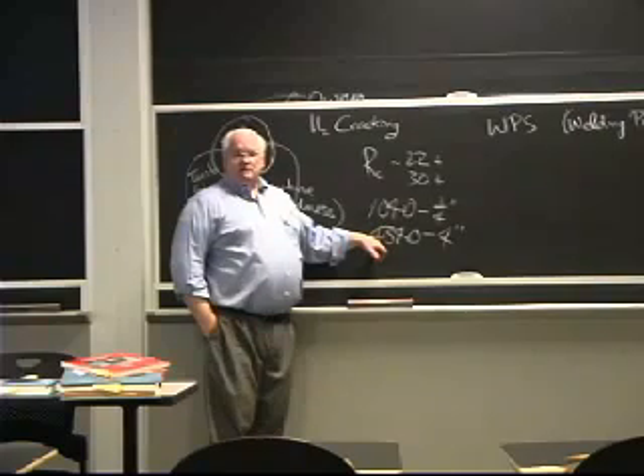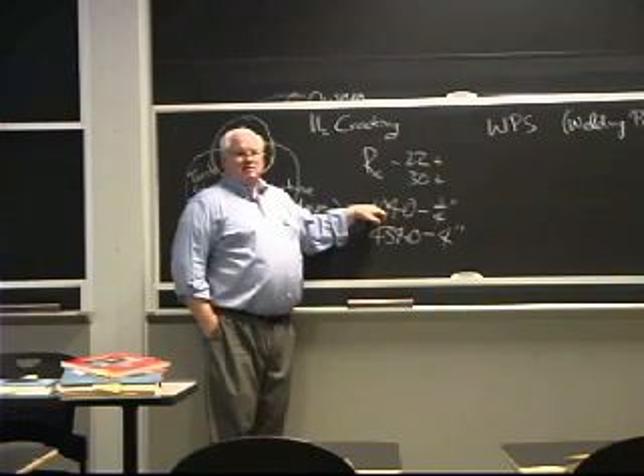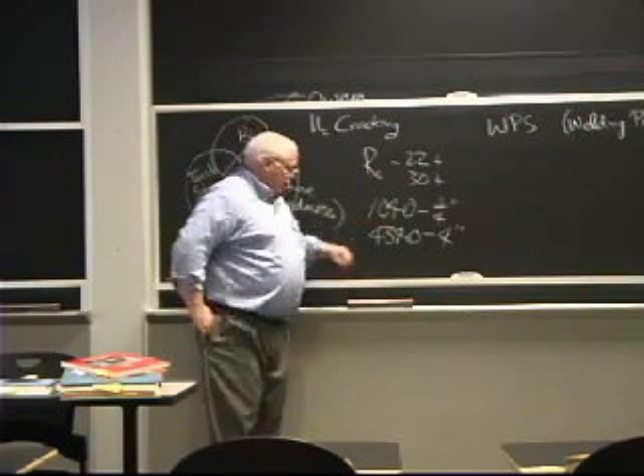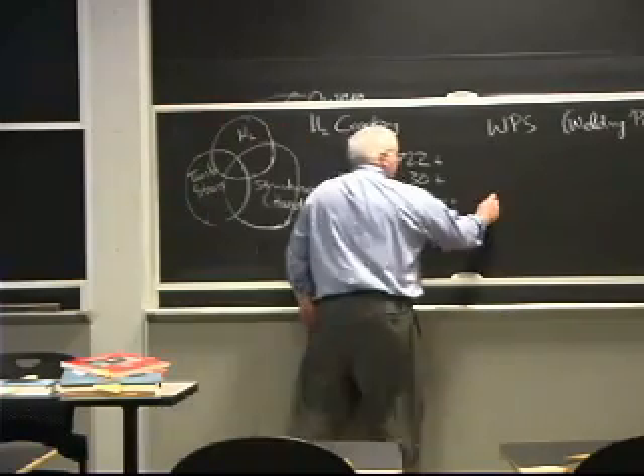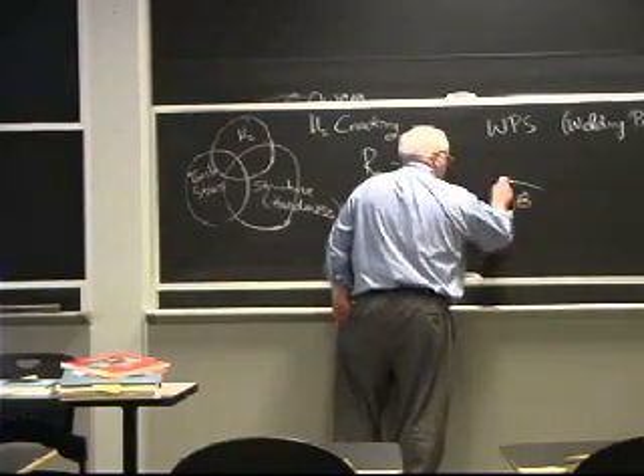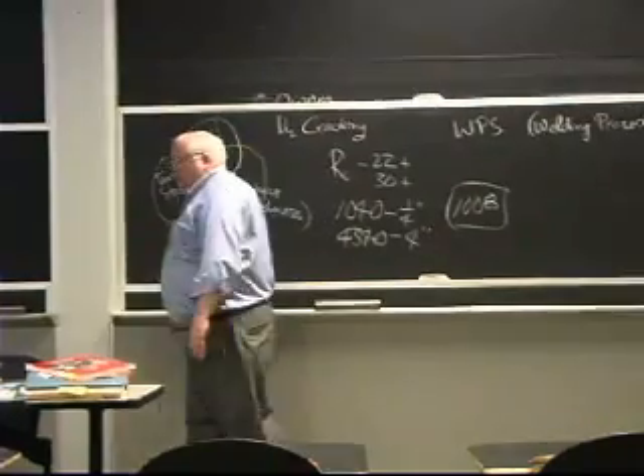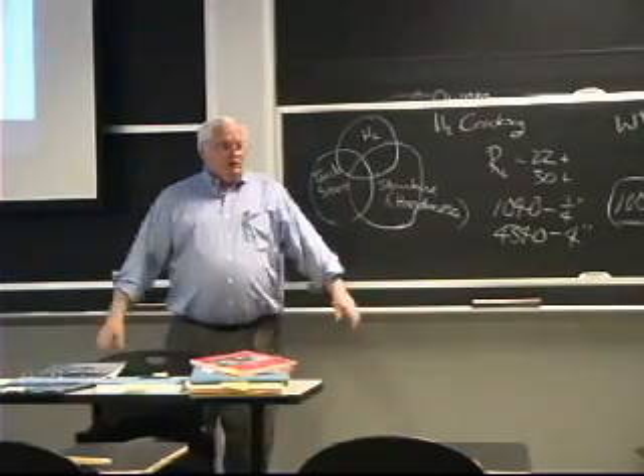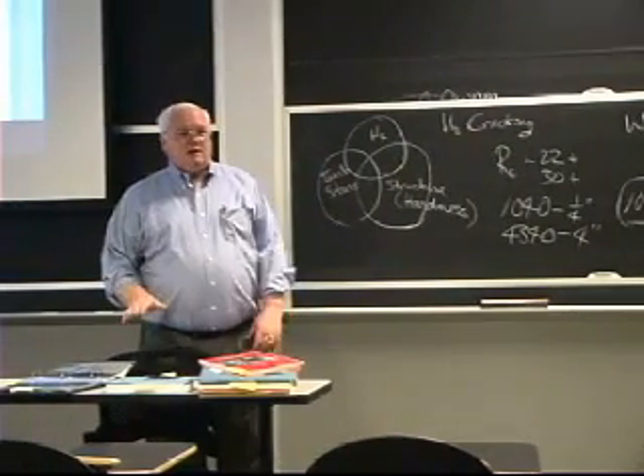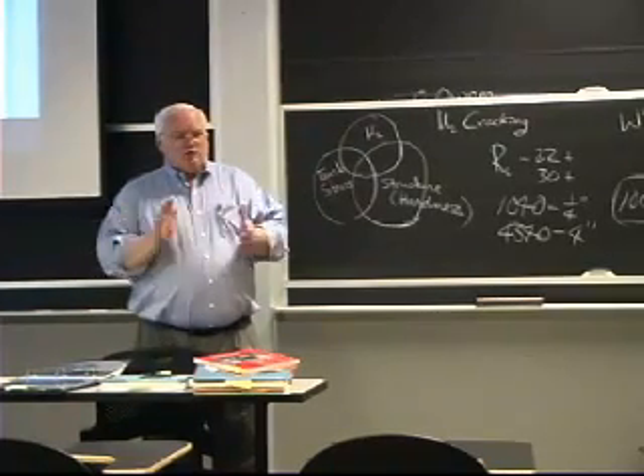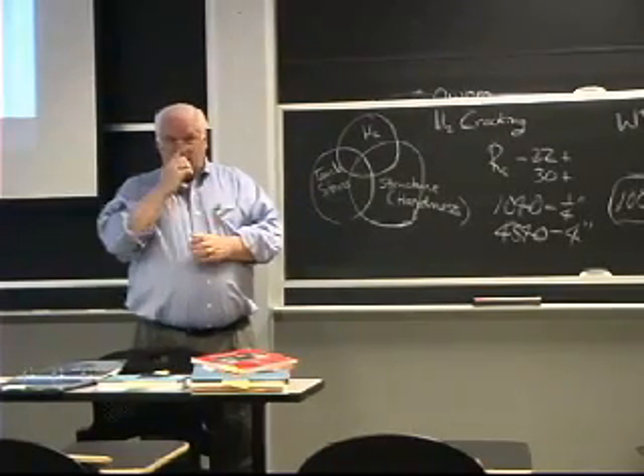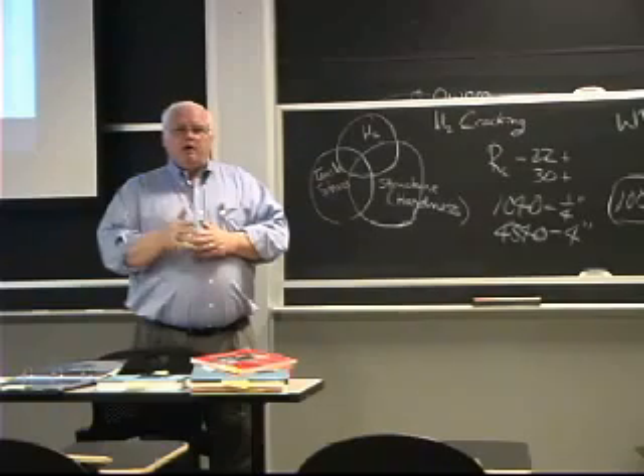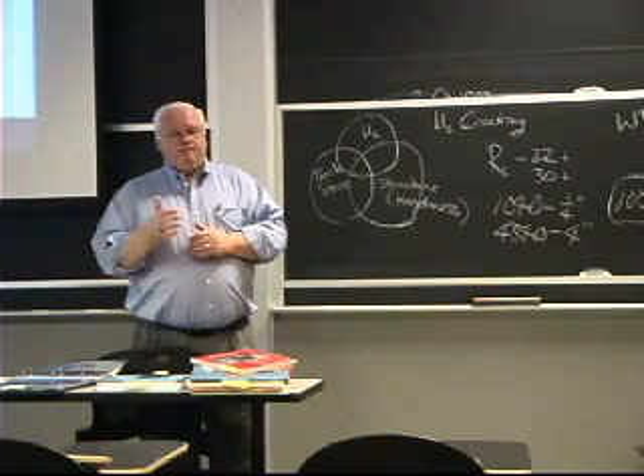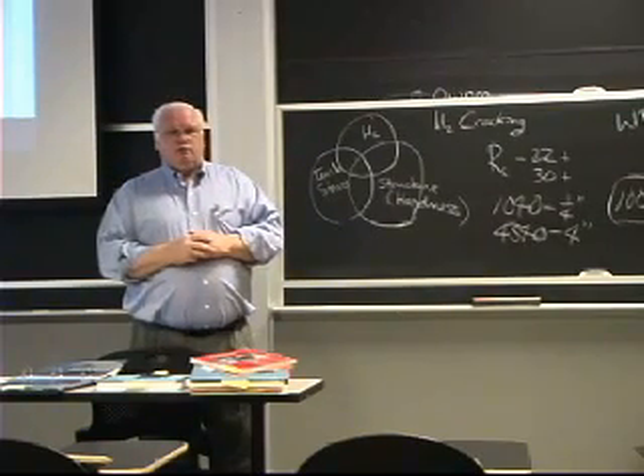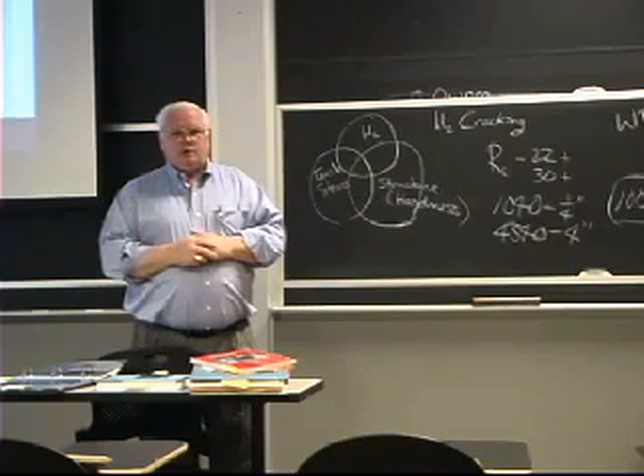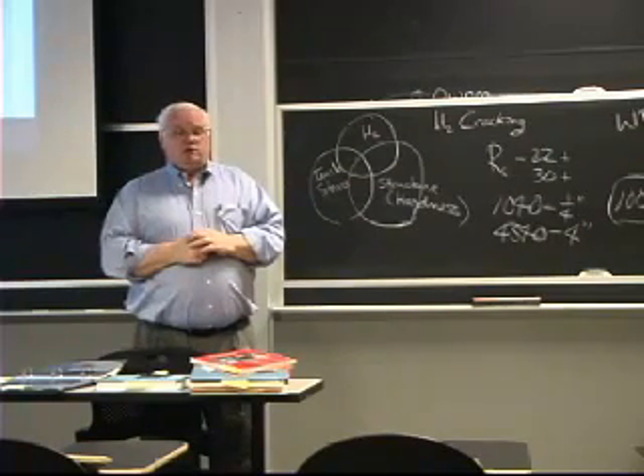This is one of the most difficult steels to weld. This is medium, okay? The lower the carbon, the easier it is to weld. A 1008, which is what we used to make automobile bodies out of, if you can't weld 1008, you really ought to get out of business, okay? Because it's not much more than iron with very little carbon. It's basically almost pure iron. Put a little manganese in and silicon to give resistance to oxygen and sulfur, but other than that, it's mostly just a low carbon iron.